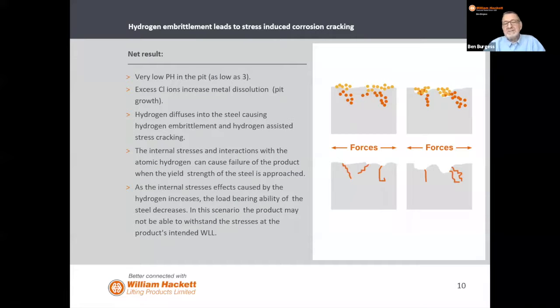So what happens as the hydrogen atoms go into the steel? They're drawn towards the grain boundaries, the dislocations, etc., and they gather at the areas of greatest stress. Typically, that's around the crown of the product. As they do so, they create internal forces, and those internal forces can then reduce the effective working load limit or load-bearing ability of the product. This comes down in simple terms to the grain structure.